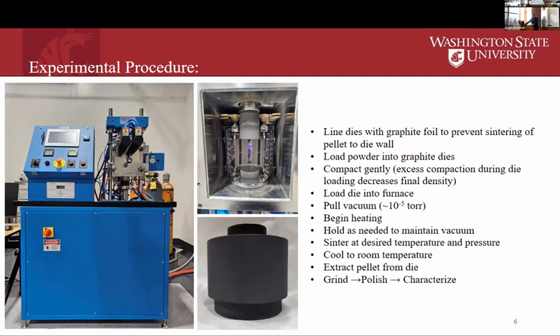During the heating process, no matter how much calcination and other steps you do, you inevitably get some off-gassing, especially at very high temperatures, and you start to actually lose yttrium and oxygen off of your sample matrix. Having to pause to maintain vacuum is actually a huge problem, because every time you pause, it increases the length of your sintering window, which allows for excess grain growth, something you have to be aware of.